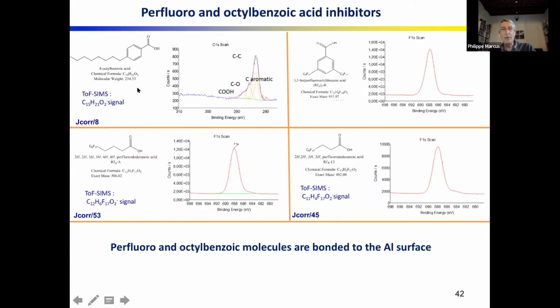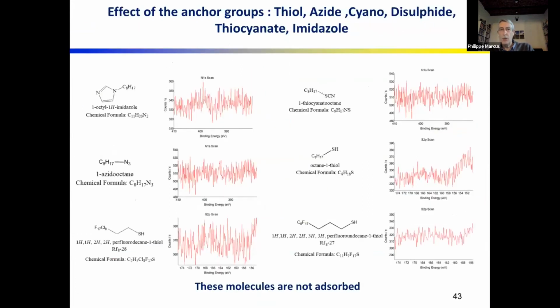And on the same material with the same inhibitors, we did measurements in collaboration with the lab in Ljubljana on the corrosion current. And what is shown here is the change of corrosion current provided by the molecule. So now what we are doing is relating the advanced surface analysis, showing whether the molecule is bonded or not, with the corrosion test that tells us what is the beneficial effect of the molecule.